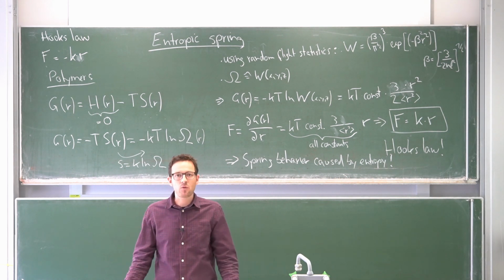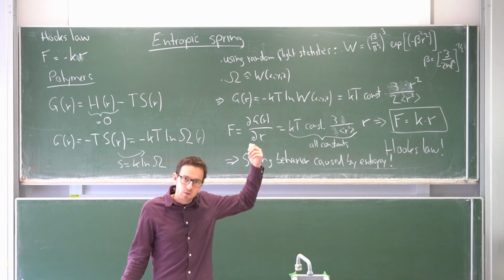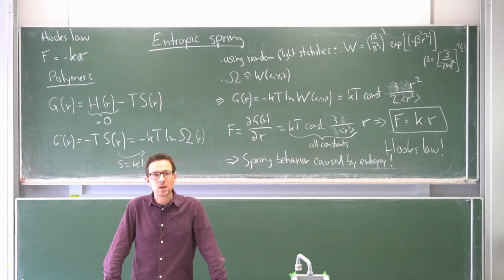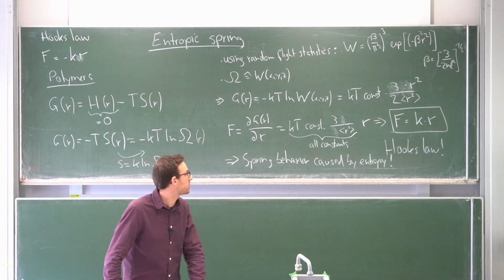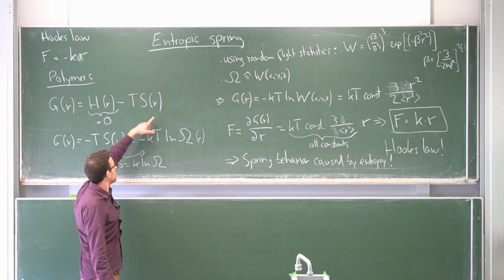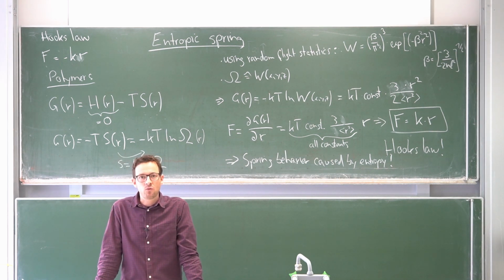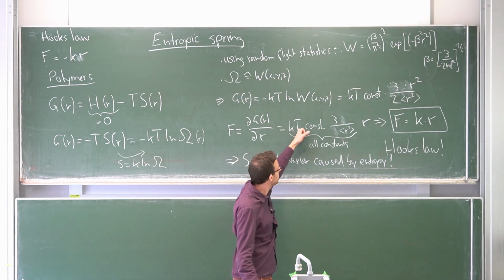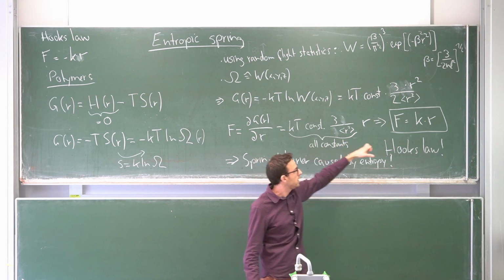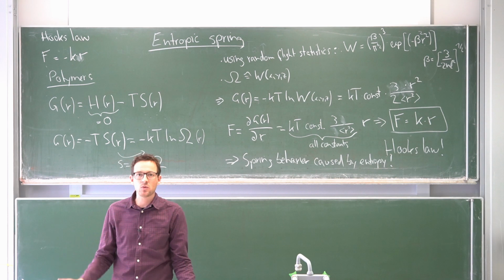So how about this negative thermal expansion coefficient? How can we rationalize this? Well, we already know that entropy plays a big role. This is what you see here. One could argue that entropy is of course always stronger the higher the temperature is. This comes from this Ts term here. So this would already tell us that with increasing temperature, we get a stronger force, a stronger spring constant. You even see this here. You have this temperature term here. This relates to k. If I increase temperature, k goes up. This means that the force bringing the spring together increases.